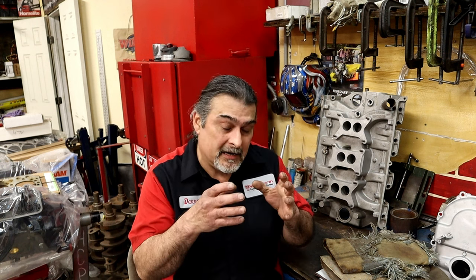All Ford Escorts cracked. So I started, let me weld the Ford Escort head. I had trouble. The crack got further. I could weld it, but 1 out of 10 may work, and 9 failures. It didn't withstand a pressure test. Even if it was a good weld, it still had little pinholes and bubbled through it. In a combustion chamber, it has to be airtight. I just couldn't get it done. Even pressure testing, I was having failures.